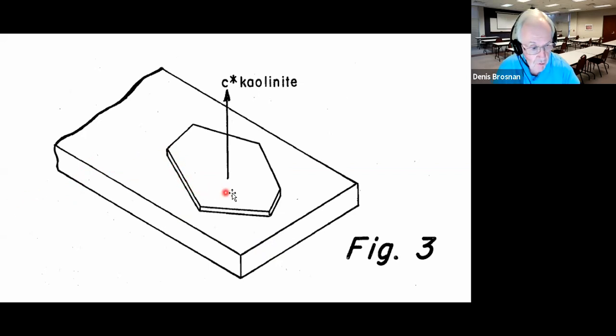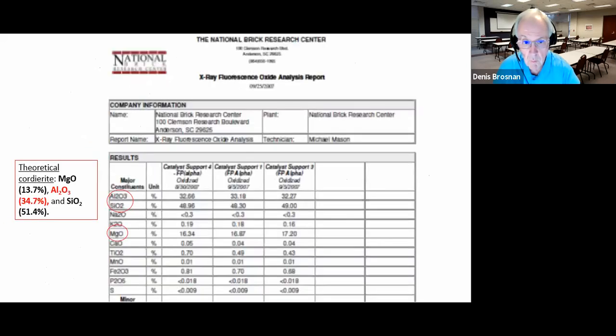this particular alignment of kaolin crystals is important because the end result is that the cordierite crystals are going to grow on top of these residual platelets. And if they line up so their low expansion direction is in this direction, on the average, then we're going to have low expansion coefficients in the device that we fire. Wonderful patent.